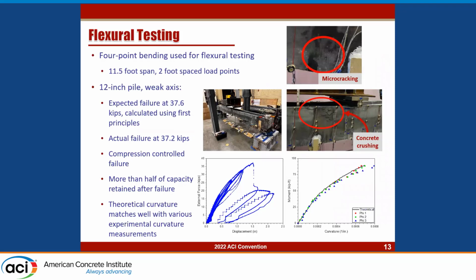And most recently, we've begun flexural testing. We started with the 12-inch pile in the weak axis bending direction. All of our flexural tests will use 4-point bending. For this one, we have an 11.5-foot span with 2-foot spaced load points. We calculated our expected failure before testing at 37.6 kips.